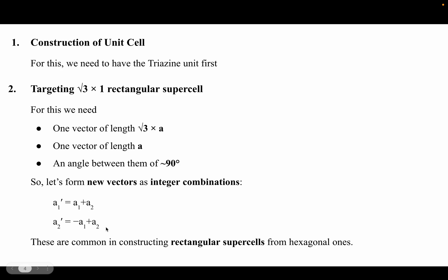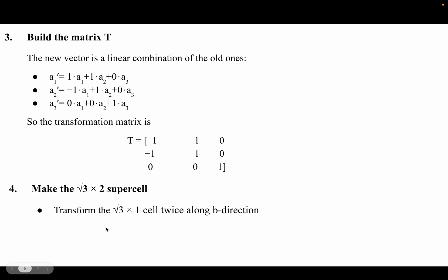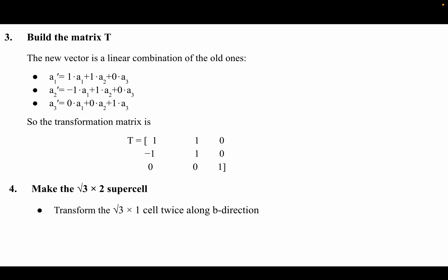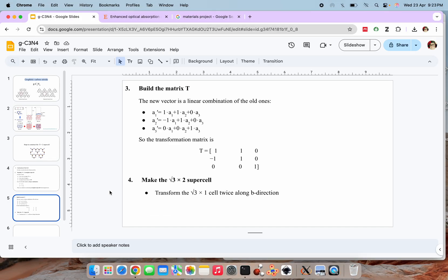For that, we will construct a new set of vectors: a₁' = a₁ + a₂ and a₂' = -a₁ + a₂. The next part is to write a transformation matrix for the root-3 × 1 unit cell. The transformation matrix is: [1, 1, 0; -1, 1, 0; 0, 0, 1], keeping the z-axis unchanged. Then we construct the supercell by doubling the b-direction, giving us the root-3 × 2 supercell of graphitic carbon nitride.